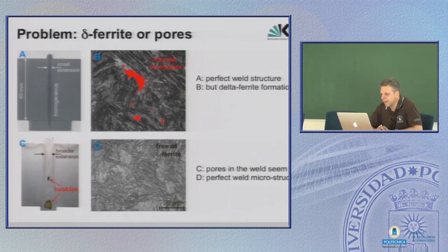Then again we said, okay, no problem. We have the machine, the knowledge, we can push many buttons and change parameters, and we really did it. I don't want to go through all these things. Here is just another example with a variation of many things. And okay, we have been able to avoid delta ferrite, but then we ended up with big bubbles in the weld line. So, a long story and a short conclusion: we have been able to produce a good looking weld with delta ferrite on the one hand, or a delta ferrite free weld but with big bubbles inside. In the end, all useless.